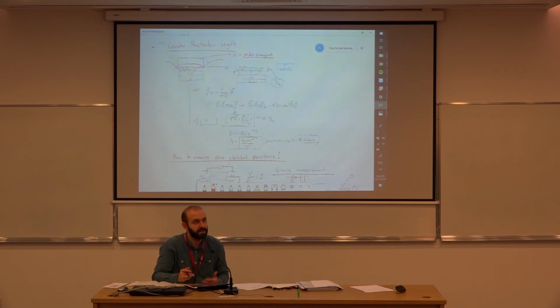But then you're also right in the sense that beyond a certain critical magnetic field will destroy the superconducting order. But I don't think it's interscattering of Cooper pairs. Rather, with the magnetic field you provide enough energy to separate this Cooper pair. So you split, basically, spin up and spin down electrons. But I'm not sure if we can say that this is scattering of Cooper pairs, because the way we think is still like fermions, right? You're thinking that two fermions cannot occupy the same state, so they must scatter, but no, they are bosons that are living in the ground state of the system. So the scattering events are either highly suppressed, or we don't even have a scattering amplitude, because the scattering criteria is not satisfied. Okay.